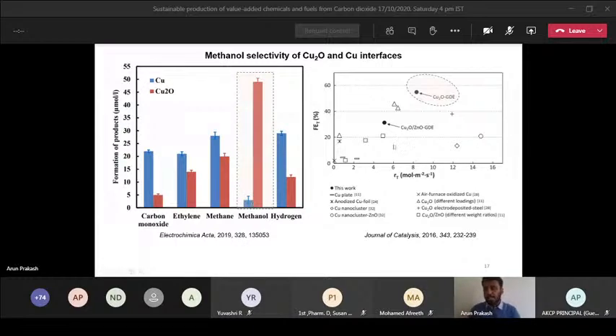And as I told before, instead of using a normal electrode, if you use a GDE, gas diffusion electrode, the performance increases significantly, almost twofold, and as I told, even 10-fold increment is possible to achieve. In the case of the cuprous oxide, zinc oxide system, they have achieved around twofold, from 30 to 60% Faraday efficiency. So go for gas diffusion electrodes.